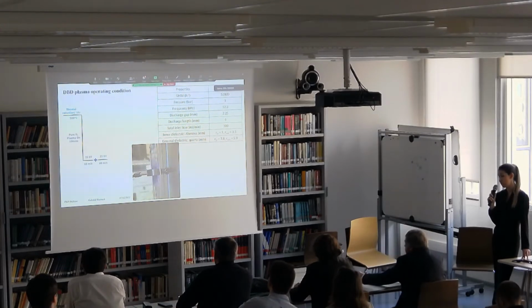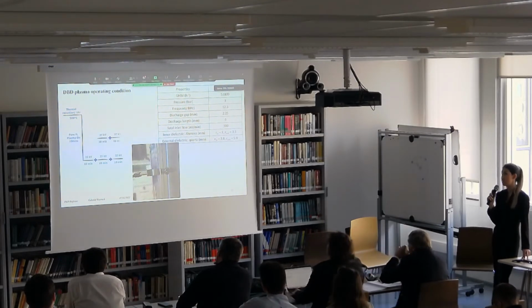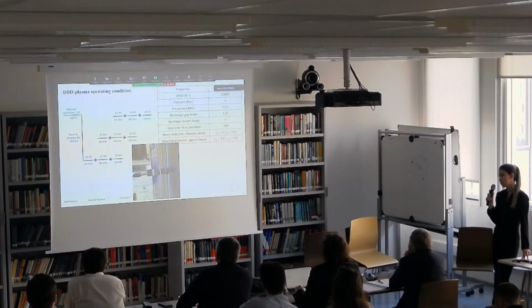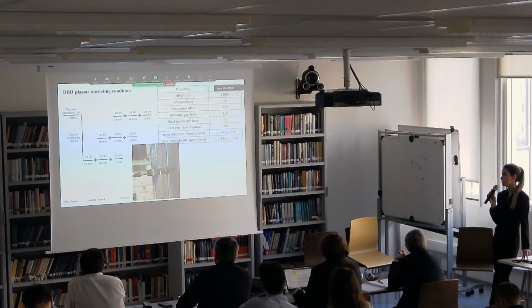Similar to the thermal reaction, the catalyst is thermally reduced and moved to the plasma reactor. Then it will be flushed by pure hydrogen and plasma for 10 minutes in order to clean the surface. Then the performance will be done at 3 different voltages. At each voltage, the condition will be kept for half an hour in order to make sure that the condition is stable. And then every 10 minutes, different measurements will be taken in order to analyze the result.